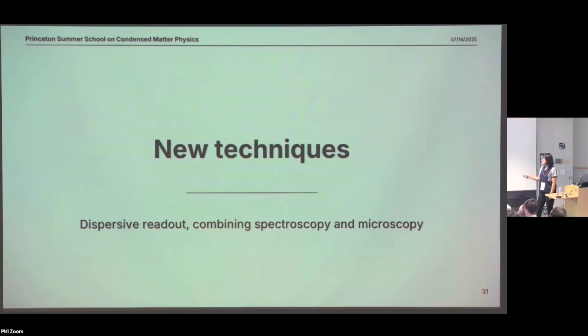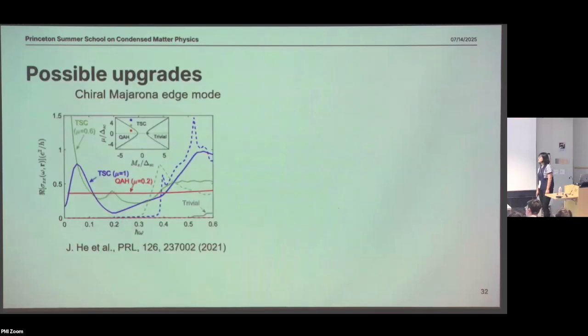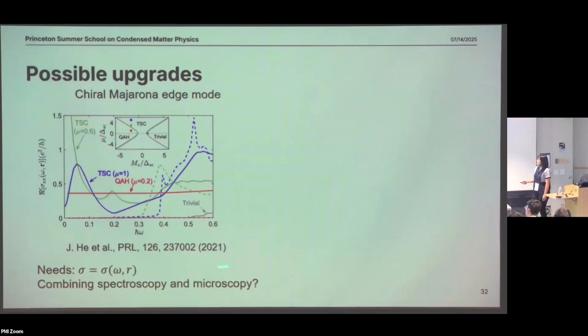And there are different limitations. One major limitation is that in many cases, to identify the physics underneath, we need the conductivity in the microwave regime not only as a function of frequency but also as a function of spatial coordinate. So it has dispersion in these two subspaces at the same time. But because of impedance matching and technical issues, combining spectroscopy and microscopy has been deemed pretty hard. And this is another theoretical prediction, saying that all chiral Majorana edge modes have distinct features of conductivity in this regime. But once again, it needs you to somehow park a tip at the edge and also measure it as a function of frequency. So that's hard.